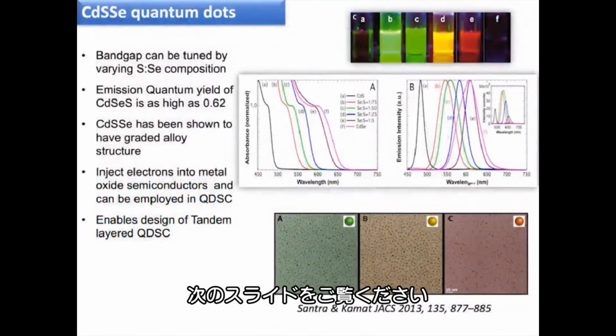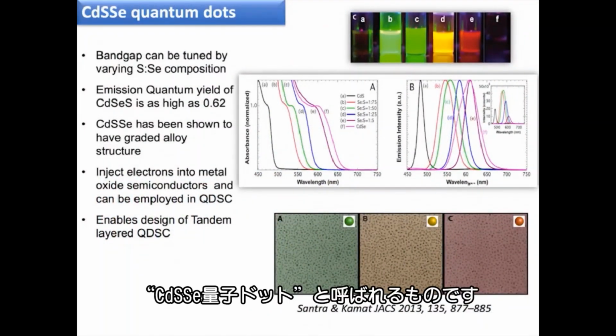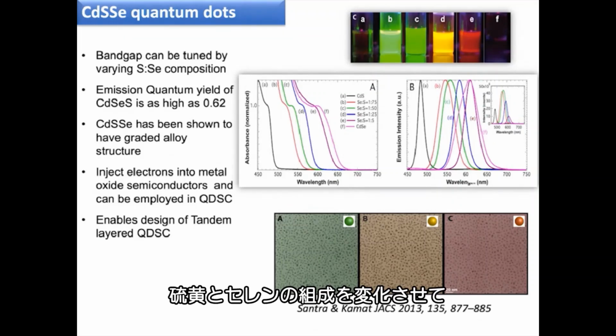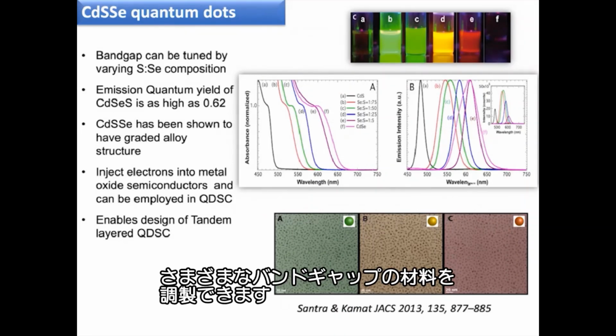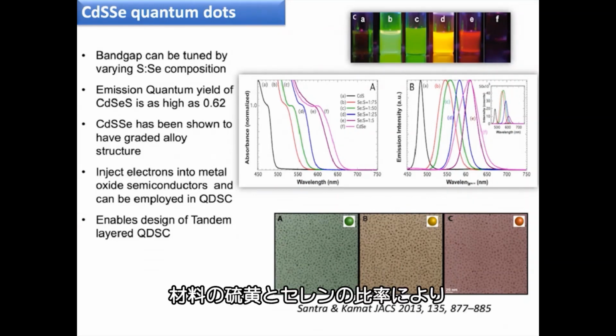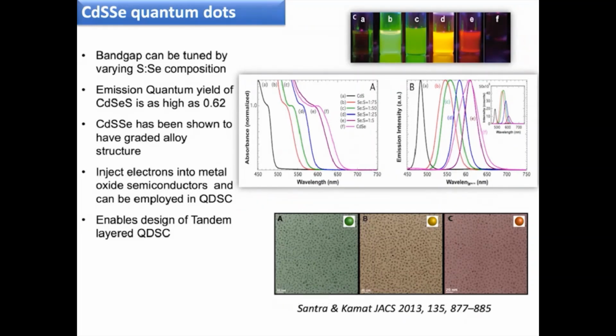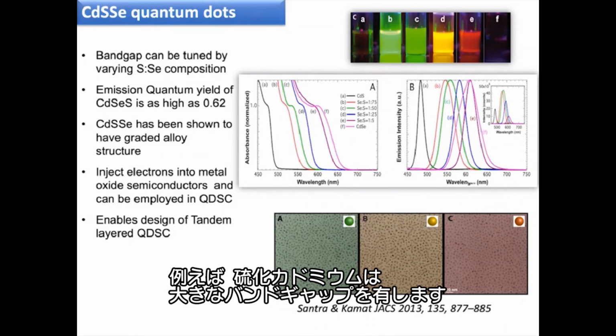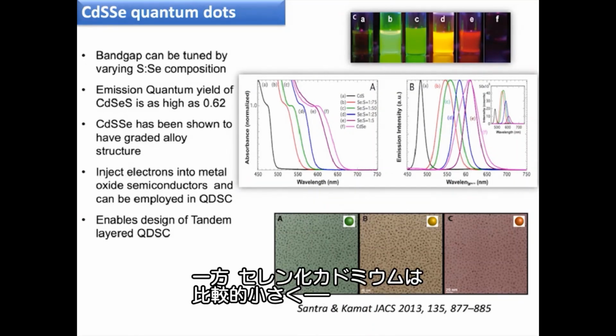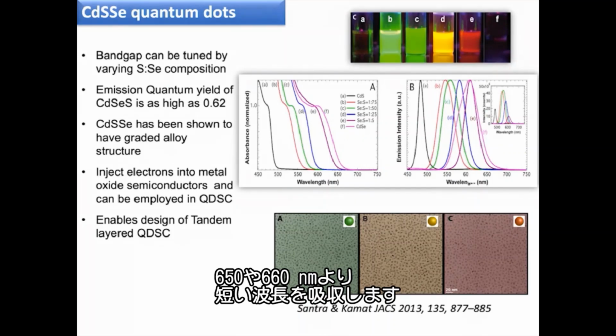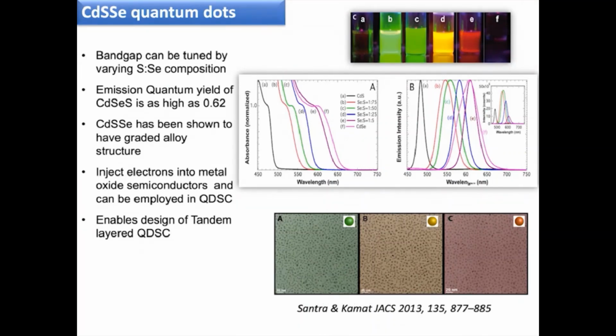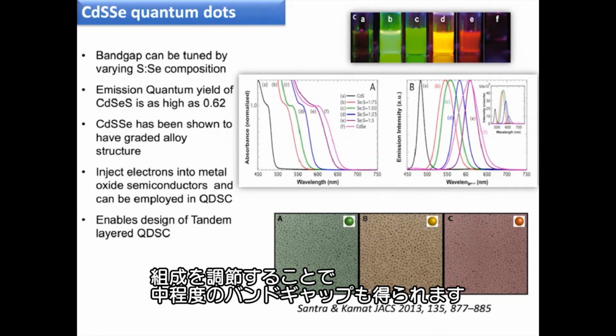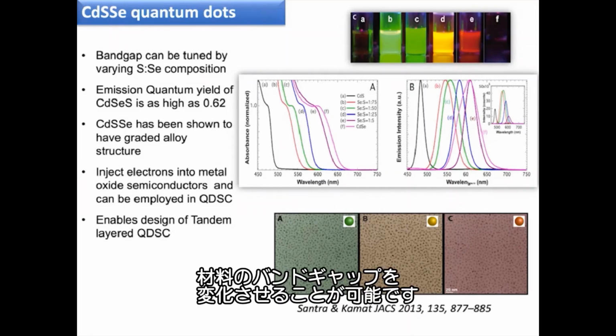In the next slide you will see what are referred to as CdS-Se quantum dots. In this case, one can vary the composition of sulfur and selenium and prepare different band gap materials. The ratio of sulfur and selenium in this material controls the band gap. For example, cadmium sulfide has a large band gap and cadmium selenide has a lower band gap, absorbing out to say 650, 660 nanometers. But by tuning their composition, one can get an intermediate band gap. This is another strategy one can use to vary the band gap of these materials.